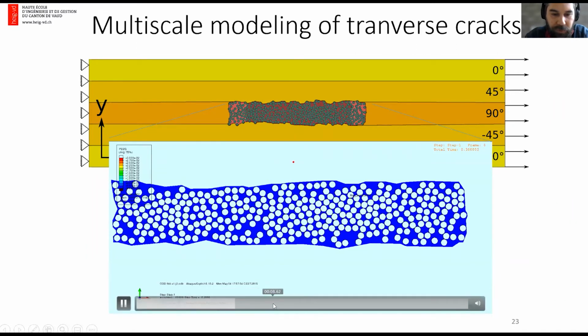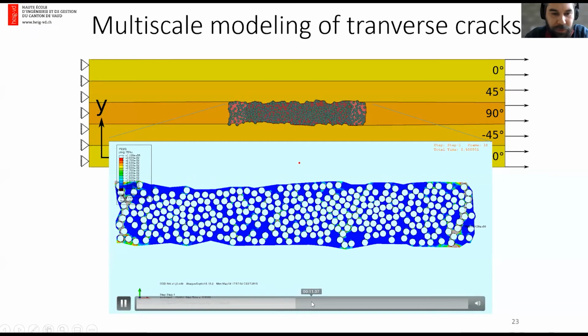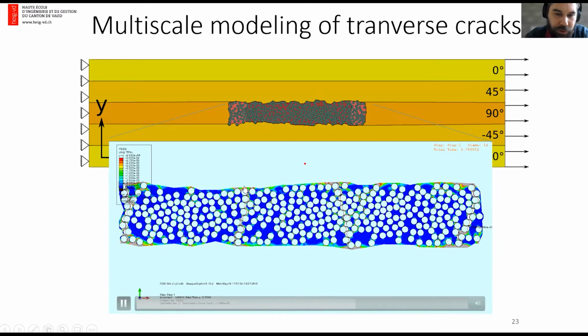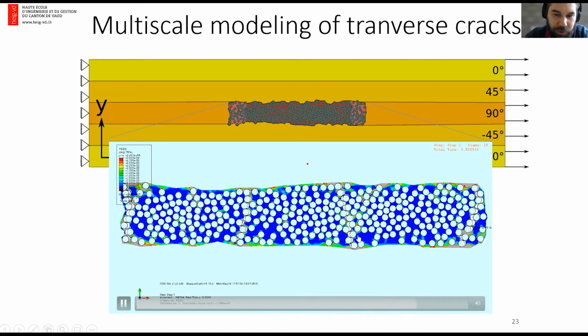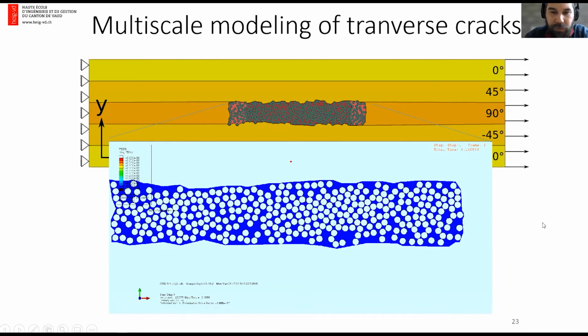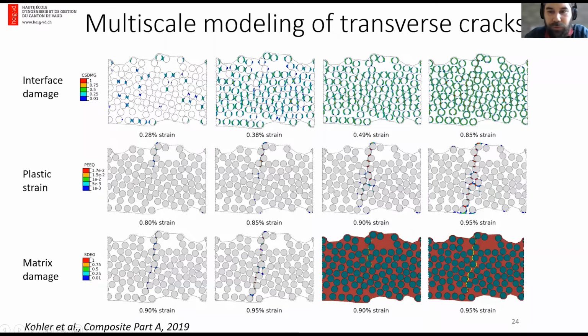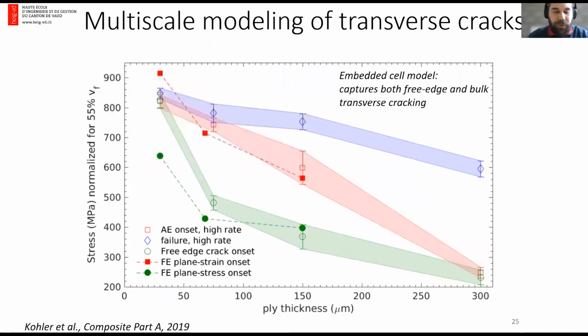So during the simulation, there's not much happening in terms of plasticity here. And then at some point we have nucleation and coalescence of small plastic damages that create cracks, transverse cracks. So if we analyze this, in the first regime of the simulation for intermediate ply thicknesses, we mostly have distributed degradation of the fiber matrix interfaces. Then we have strain localization with plastic strain that develops in preferred bands here. And this plastic strain leads to matrix damage, so degradation of the matrix, and finally coalescence of a full crack at about 1% strain.